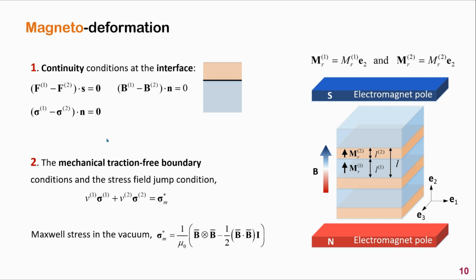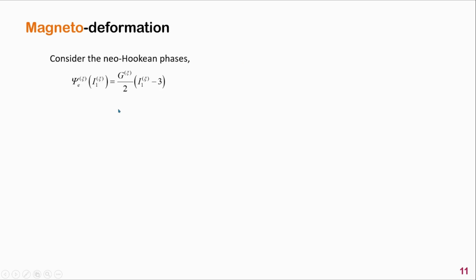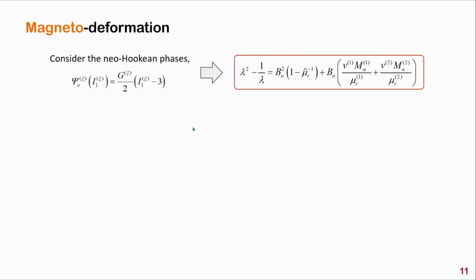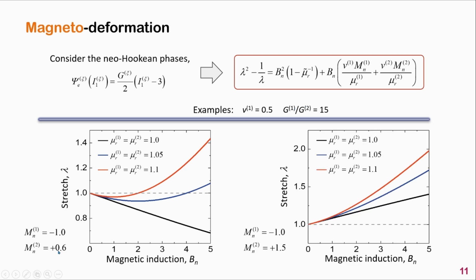Since here we didn't apply any mechanical loads, the average Cauchy stress in the laminate system equals the Maxwell stress in the vacuum surrounding the laminate. Considering specific energy density function characterizing the purely mechanical response of the constitutive material, we can obtain the stretch of the laminate system for specified magnetic induction. For example, by controlling the magnetization distribution in the laminate, including the direction and the magnitude, the laminate can be compressed or stretched under external magnetic field.